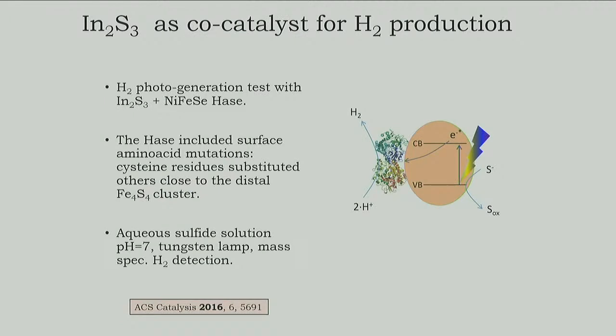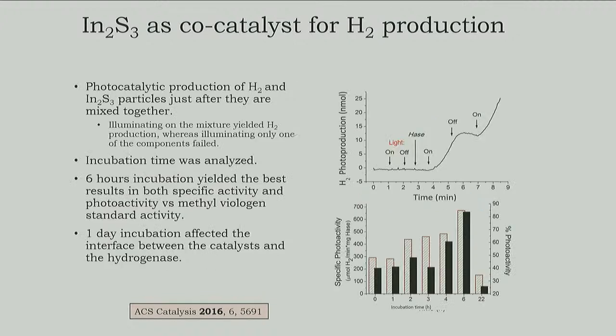And we also tested the enzyme with our semiconductors, not only with photosystem 1, but this indium sulfide, we could immobilize the hydrogenase on it, and in solution, in the absence of any kind of electrode, we could get response using a sacrificial electron donor. In this case is sulfide. When we put the enzyme here, we can see that we switch on the light, and then this is hydrogen production measured in real time with mass spectrometry. When we switch off the light, the system stops, and we switch on, and it goes up. And here is an analysis of the hydrogen production measured by mass spectrometry after its incubation time, putting together the hydrogenase and these indium sulfide particles, reaching the maximum after 6 hours.